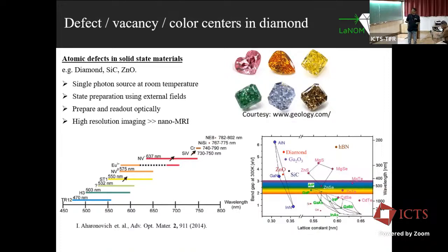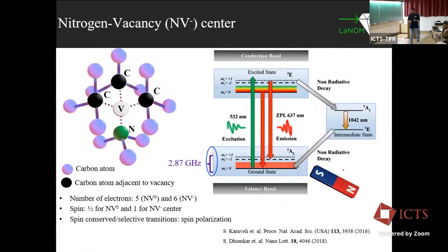This diamond has a lot of defect centers spanning from 450 nanometers to 800 nanometers. And depending on the type of vacancy or defect, you have different optical properties. And diamond is not the only material which can have these properties. There are materials like silicon carbide, even hexagonal boron nitride. It's another system which also shows similar properties at room temperature, sometimes with a better optical response.